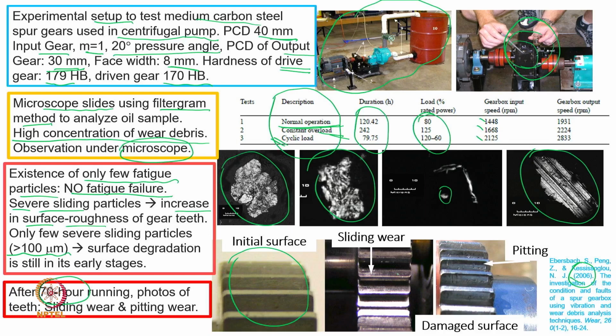They are able to see that there is a lot of sliding on the gear teeth, and we are able to see pitting of the gear teeth also. Now, even though they say there is no fatigue failure, and pitting mostly happens because of fatigue failure, that means the sliding wear is causing more problems. The area available to sustain the load is continuously decreasing, and only then will the pitting start. So the root cause in this case turns out to be sliding wear, not pitting wear as such. That is what they concluded. Of course, they are able to observe both, but sliding wear dominates compared to pitting wear in this case.